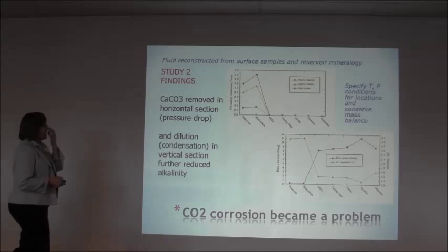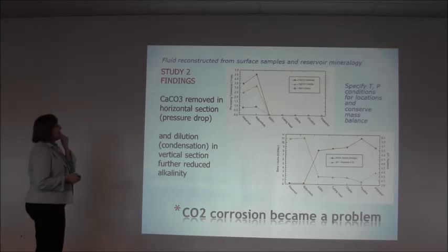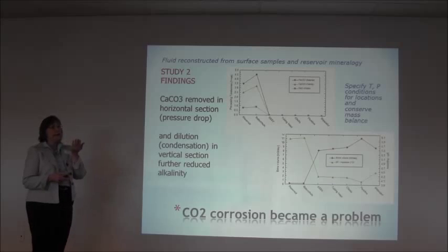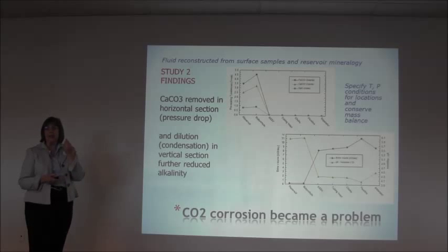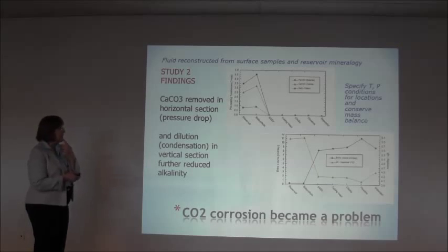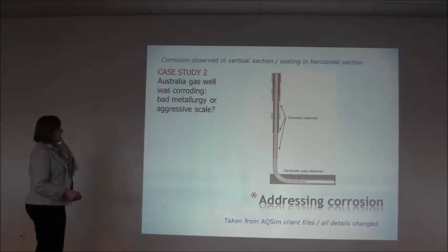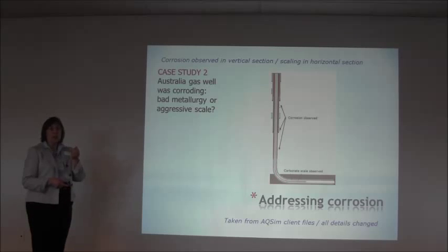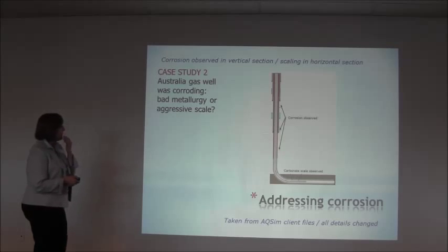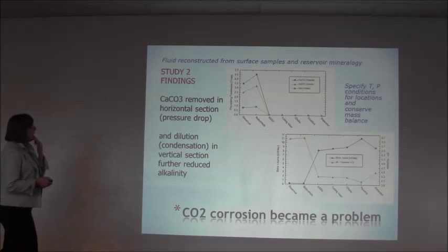So what we found was that this was really a case of alkalinity not really helping us, because alkalinity was dropping. Why was alkalinity dropping? Alkalinity was dropping because as we head back to that place in here and the pressure was dropping, carbonate scale dropped. So carbonate scale dropped, but the carbonate wasn't bound in the solution anymore. So pH is dropping, right? So that was one thing that happened.